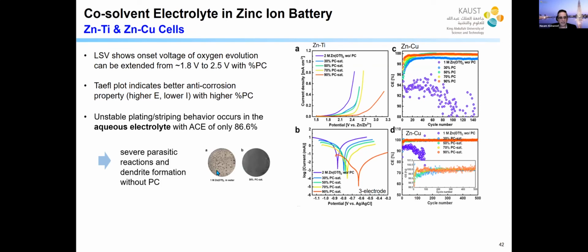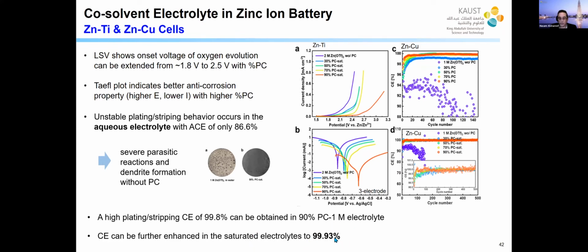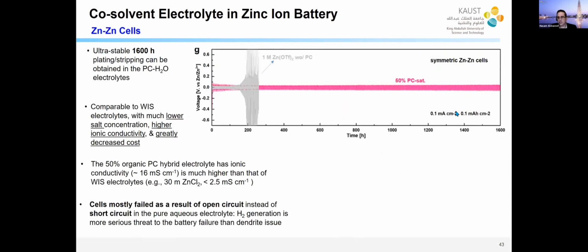And you can see here, after cycling, what happens to the zinc when you use this salt in water and when you add PC. PC clearly stabilizes it. And the Coulombic efficiency is only 86 when you have water, but it goes up to 99.8 in 1 molar PC, and it goes to 99.93 in saturated PC electrolyte. Look at the cycling performance. Similarly, with the PC, you can go to 1600 hours, which is really impressive.